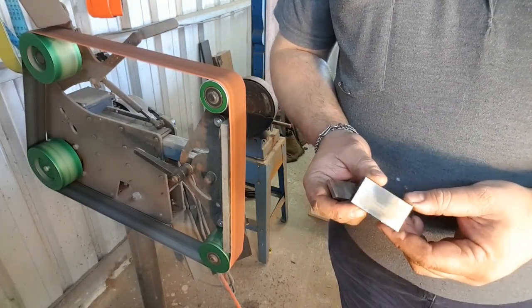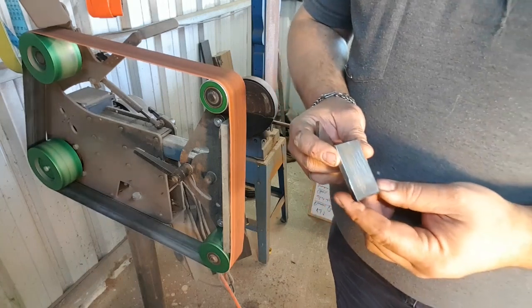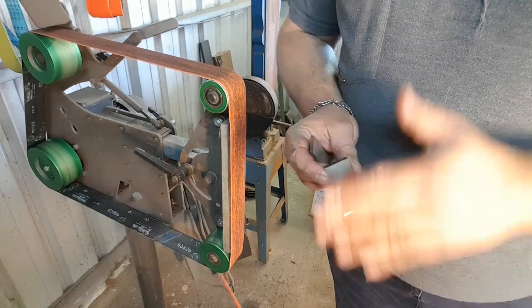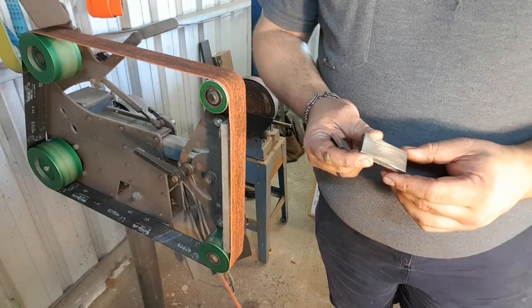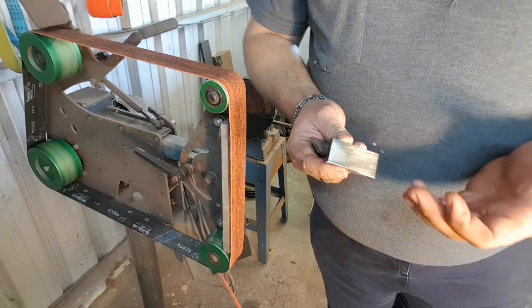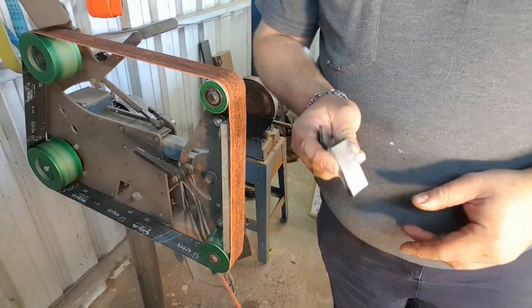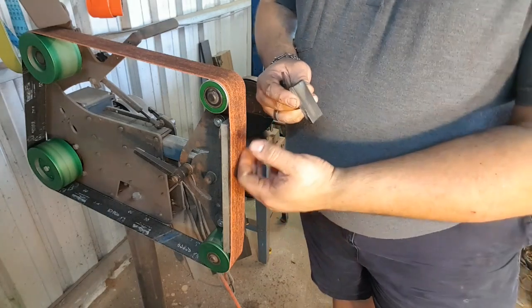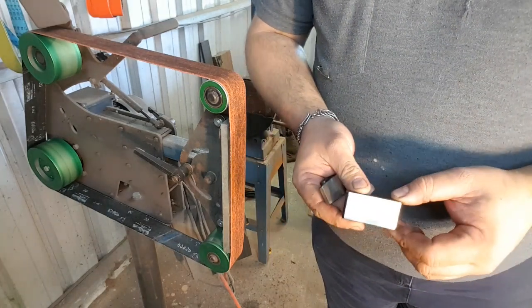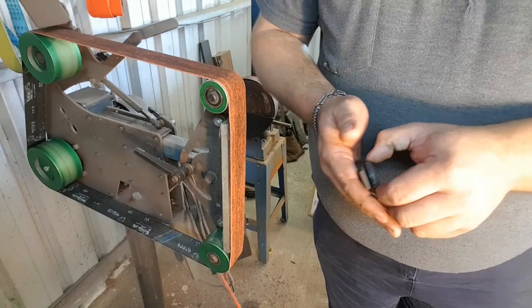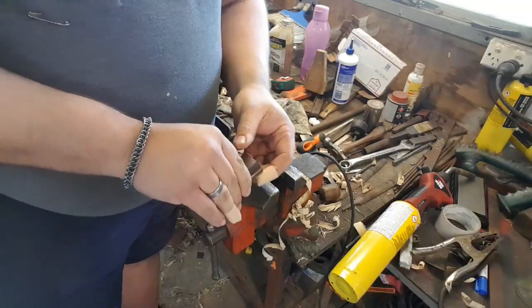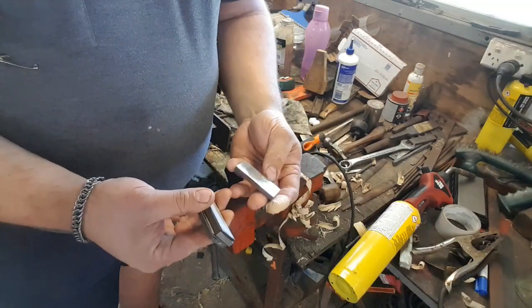And that's all it takes. In this case, I've got a very flat platen, so I don't have to worry about it too much. And I don't have to have a super clean surface as far as grit goes. This is only a very worn out 50 grit, and that gives me a nice clean surface to then weld to the other pieces. Okay, so the inside of our billet is nice and clean.